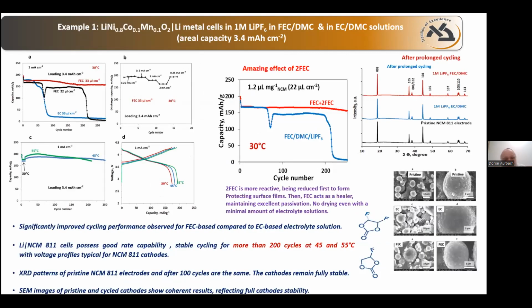Now we add another co-solvent. Now we have both of them in solution, and we have extra stabilization. These are results related to 80% nickel, and these are experiments that were carried out at relatively fast rate. So this is a nice result, and we demonstrate stabilization thanks to the presence of two co-solvents, compared to solutions where we have only one co-solvent, only FEC. And now with both of them, we see stabilization, and the electrodes remain very stable.